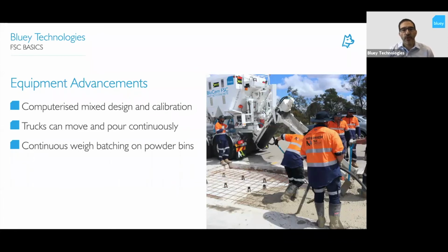We now have computerized mix design and calibration, so it's all controlled by a computer. The trucks can move and pour continuously, so you don't have to stop the pour to move the truck forward. And that's a really important feature to maintain consistency of your pour and avoid cold joints. And we also have continuous weigh batching on the powder bins, which is what I mentioned was the really big advancement where we went from volumetric trucks to weigh batching units.